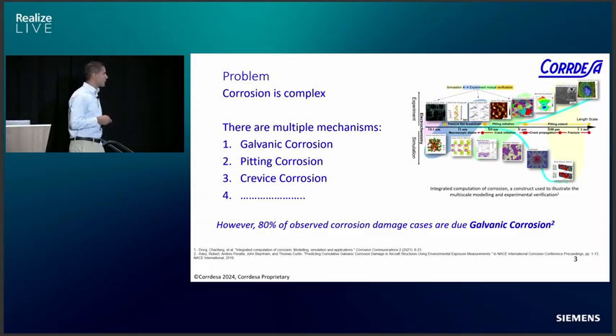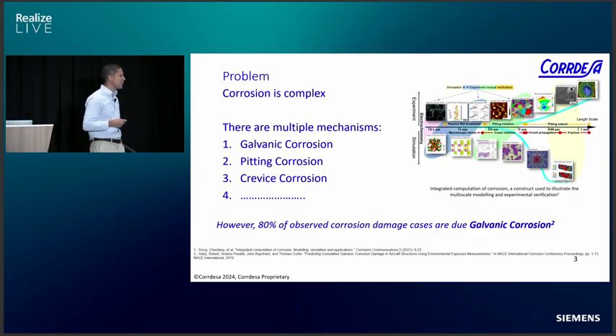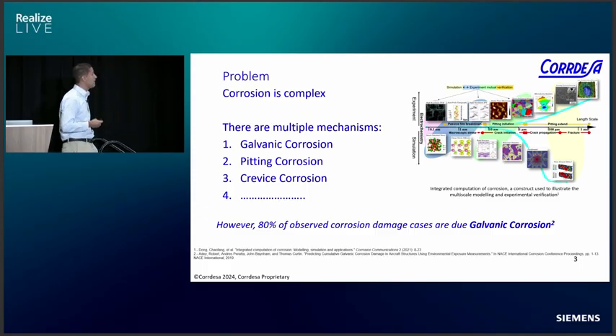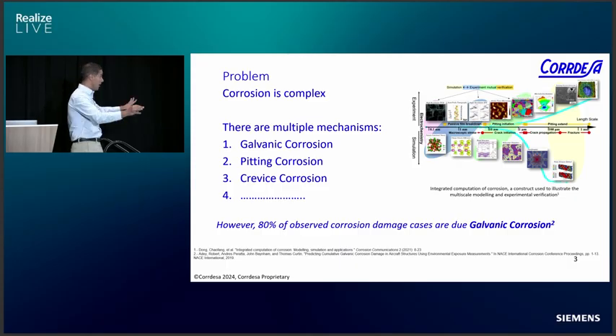But because of the complexity of the problem, we should not stay away from modeling, because there are other areas like turbulence, for example, combustion, chemical reaction, that are as complex as corrosion, but we are seeing that folks are making really good progress in those areas. But we at Cordesa still see that corrosion is still in the Stone Age. We have really fast computers, we have really efficient numerical methods, but still we don't see the community embracing CFD applications, or not even CFD, applications that we have developed to mitigate corrosion risk. And more importantly, 80% of all these problems are related to galvanic corrosion. So if we focus on that 80%, we're going to make a really, really positive impact in the industry, and of course in other areas as well.